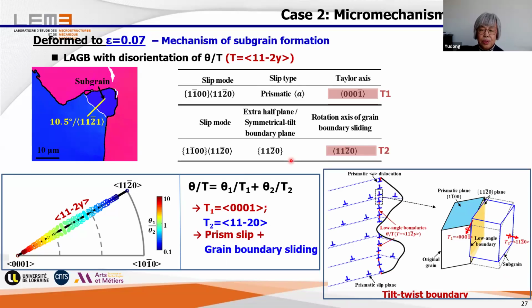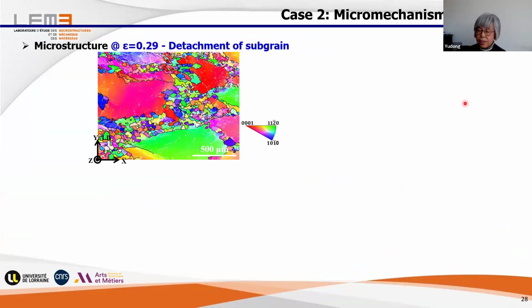Anyhow, we deform the material at a very high temperature. And so you see, with boundary sliding, this part related to this part along the axis perpendicular to the extra half plane, we form this so-called tilt-twist boundary. This is also mentioned in the literature. And so it's very fine. And then continue.